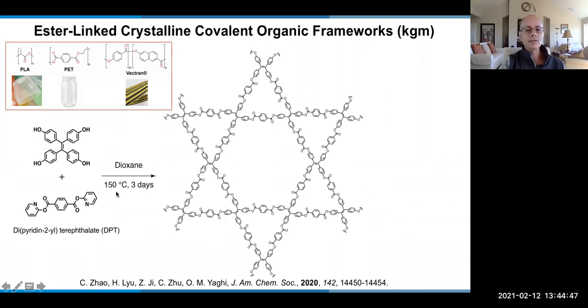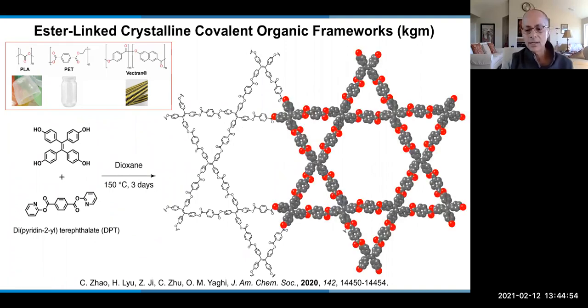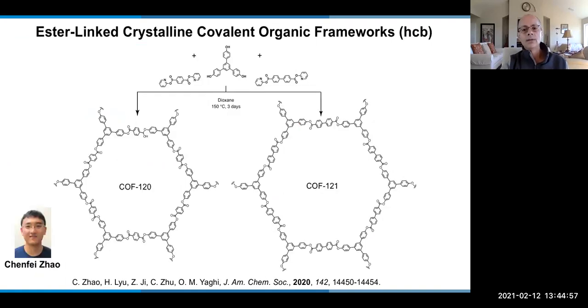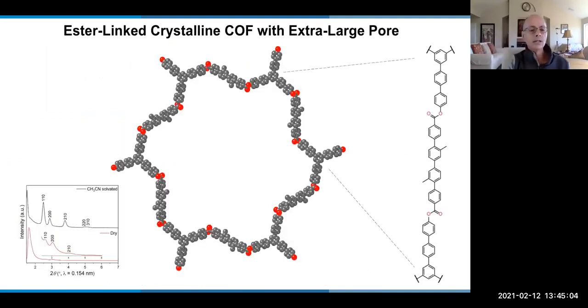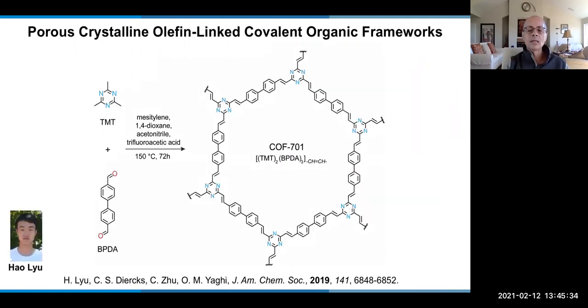So 150 degrees instead of 120 degrees, but these are nice structures based on the ester linkages. Here is more of those. And he even could get an X-ray powder diffraction of a structure as porous as this one. This is one of the largest pore crystals known. The linker is made from a series of 10 phenylene units. And so this tells you the range of things that could be done and really the wide variety of metrics that could be accessed.